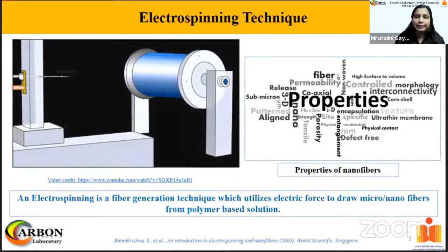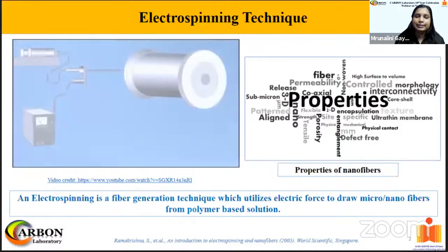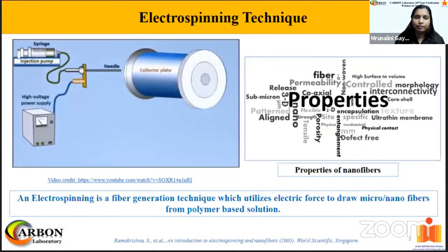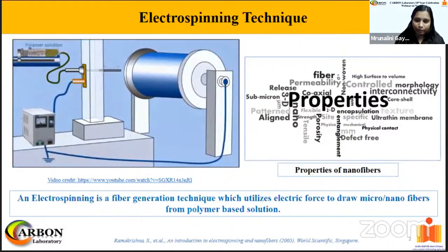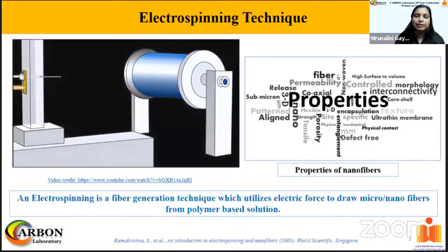Now, three different forces interplay at the verge of the needle tip. Surface tension and viscoelastic forces act inwardly, tending the drop to be spherical in shape, while Coulombic forces act outwardly, stretching the drop into a conical shape, termed the Taylor cone. When Coulombic forces exceed the other two, a polymer jet with like charges erupts and travels to the oppositely charged collector. While traveling towards the collector, the solvent evaporates and dried nanofibers in the form of a continuous non-woven matrix are deposited on the collector. These nanofibers possess high specific surface area, high porosity, interconnectivity of fibers, and facilitate surface functionalization and easy encapsulation of active molecules such as drugs.